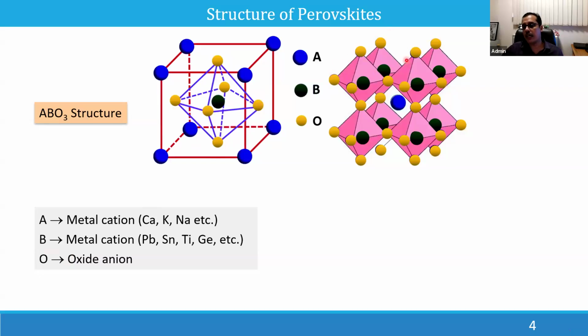And several of these octahedral structures are combined together to form a 3-dimensional structure. By forming the 3D structure, voids are formed, and these voids are filled with the A cation. That is needed for the structural stability as well as for the charge stability. Because it will compensate the excess negative charge on the octahedral structure, since there are many oxygen ions and the negative charge is not compensated by the B cation alone. So you need some positive cations to compensate the charge of these oxide anions, and that is done with the A cation. So this is the structure.